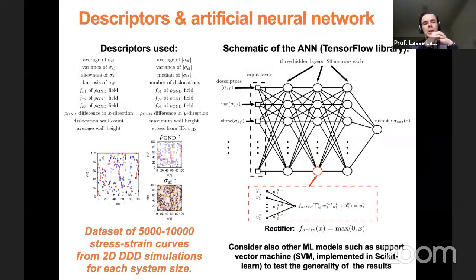So to get started, we first generated the big data set, okay? So we created a bunch of these initial configurations with this procedure where you first put your dislocations in the system randomly, let them relax, and you get such a configuration, and repeat several times, so like 5,000 to 10,000 times, so a large data set.